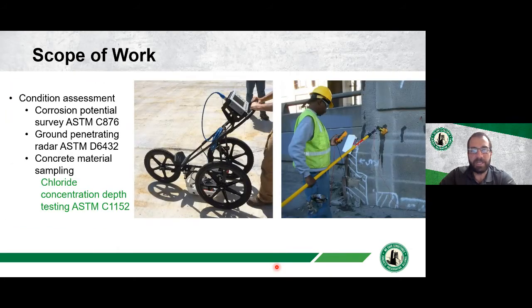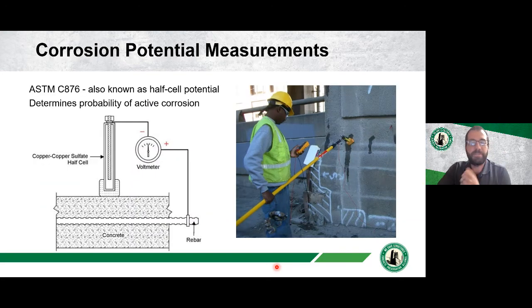So we were asked to come and do a condition survey of the structure. We did corrosion potential measurements, ground penetrating radar, and chloride sampling of this structure. Corrosion potential measurements are where we take a reference electrode and measure the potential of that reference electrode against the rebar in that structure. And the potential of that reference electrode versus that rebar will tell us the probability of active corrosion. Here you see this gentleman doing corrosion potential measurements on this wall. We've previously sounded the concrete, and so we know where the delaminations are.